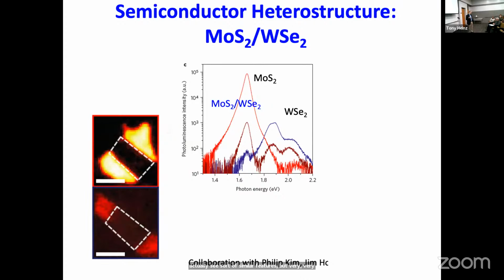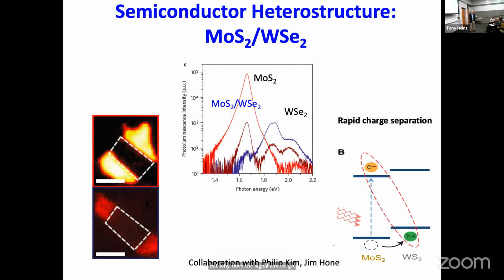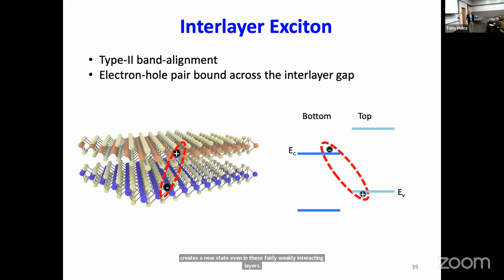So that they wouldn't shift a lot is reasonable because the interactions, I mean, I talked about the screening effect, but they're not like dramatic shifts. But why does the signal almost go away? And the answer is that you have a new thing that can be happening, which is that either the electron or the hole in the exciton will hop into the other material, because we understood already that you had the staggered band structure. So then you would separate the electron and hole, they wouldn't be as near each other and they wouldn't emit as well. And this kind of rapid charge separation creates a new state, even in these fairly weakly interacting layers. So this is something that has now come to be understood as an interlayer exciton. You have separated electron and hole in the two layers.